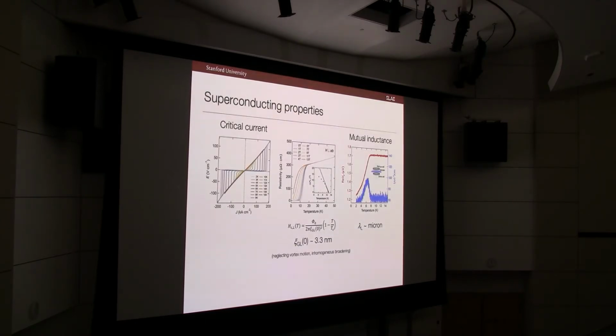So if we look at the early superconducting properties of this system, it exhibits a critical current density at that point of about 0.2 megaamps per centimeter squared. Recently, that's gone up by about an order of magnitude as samples get better and better. We can put on a perpendicular magnetic field to suppress superconductivity and therefore estimate the superconducting coherence length. That turns out to be typically 3 or 4 nanometers in scale.